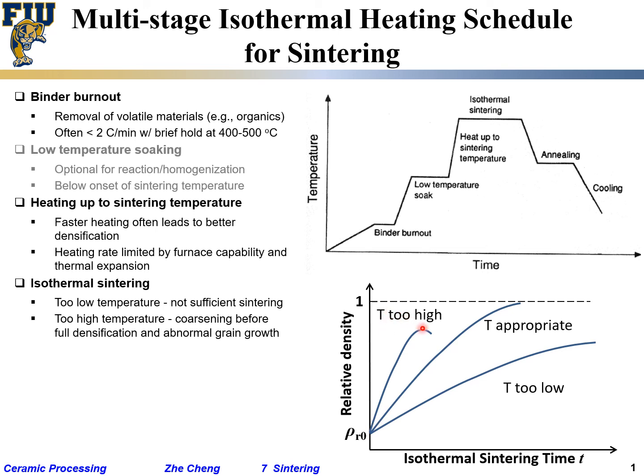Make sense? On the other hand, if your temperature is too high, it initially increases very fast, but kind of saturates at a certain location, because the particles are already too big. Meanwhile, you still have a lot of porosity that hasn't been removed. And once the particles are very, very big, the surface becomes flat. There's no further driving force for densification to occur. So somewhere in between. Somewhere in between. That's your sweet spot. Okay?